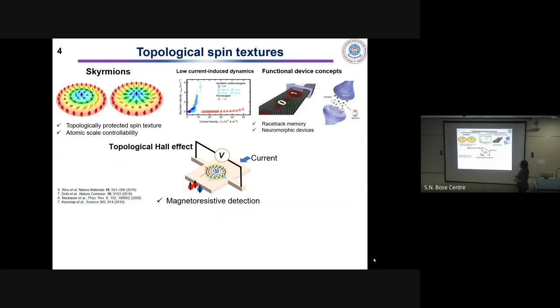So what is important is that the existence of skyrmions in a magnetic material can be detected using a simple magnetoresistive technique, that's the topological Hall effect. And what happens is that because of the presence of these skyrmions or this kind of textures in the system, the conduction electrons feel an additional scattering, an additional contribution to the transverse Hall resistivity depending on their up and down spin. That's the topological Hall effect. And I'm talking about this because this is what we are going to use in our upcoming results.